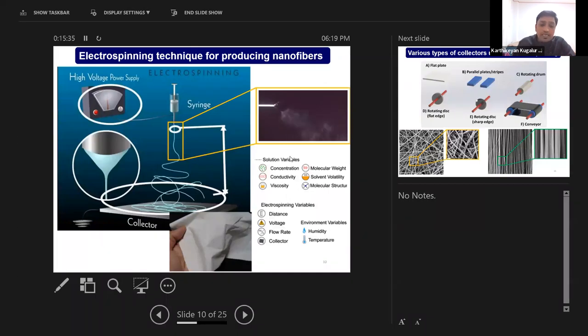There are several variable parameters which can influence the nanofiber diameter. Mainly, since we are using a solution, there are three different things: the concentration of the solution, the conductivity of the solution, and the viscosity of the solution. By increasing or decreasing the concentration, you can change the diameter of the nanofibers. Similarly, the molecular weight, the solvent volatility, and the molecular structure can also influence the nanofiber diameter.